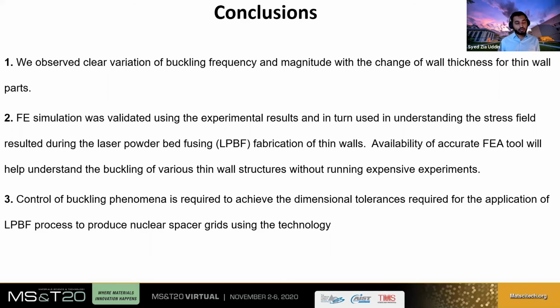In the 200 micron case, we have seen a very high frequency buckling pattern. In the 300 micron, the buckling pattern reduced a little bit. In the 500 micron wall thickness, there was no high frequency buckling observed. So this is a critical observation, and this will guide us in designing the spacer grid so that we can maintain the tight tolerances imposed on the spacer grid parts by